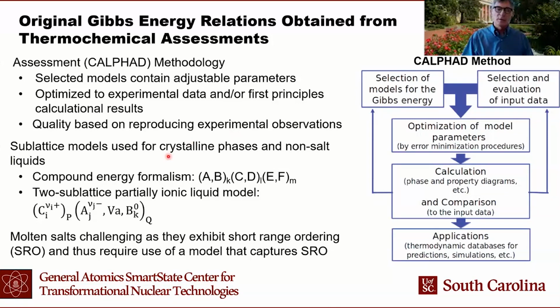For crystalline phases that are solutions, we use sublattice models such as the compound energy formalism. And for liquids that are not salts, we can use something like this two-sublattice partially ionic liquid model. So these are common models used for solid and liquid solutions. Molten salts, however, are more challenging.